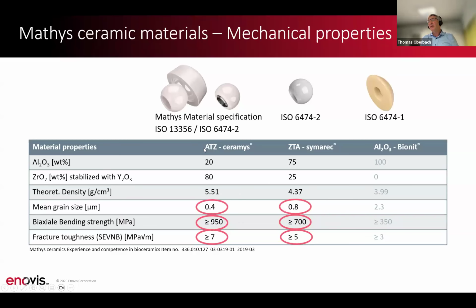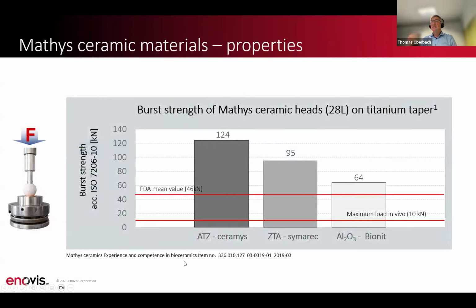If we look at the material specification and compare it with the alumina ceramic, our Bionit, then you see concerning the grain size, we reach much lower grain sizes with ATZ and also with ZTA in comparison to our alumina. The bending strength is higher, approximately 3 times higher for ATZ and 2 times higher for ZTA. And you also see that with increasing zirconia content, the fracture toughness increases. With these facts, we can also reach better properties with the implants.